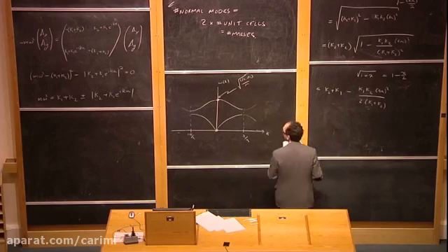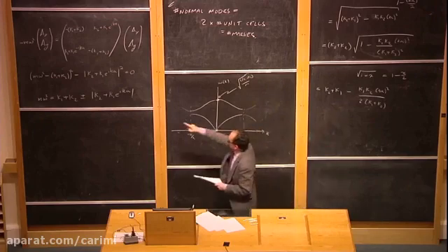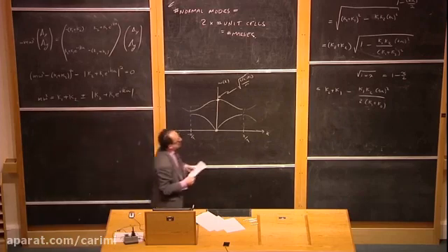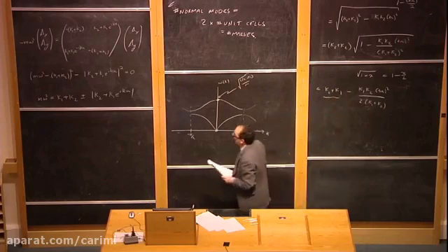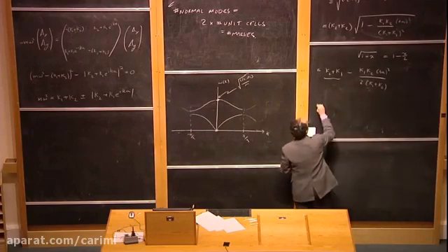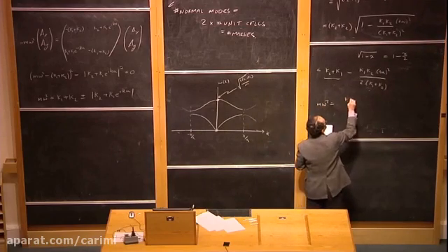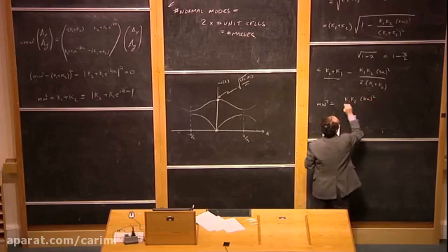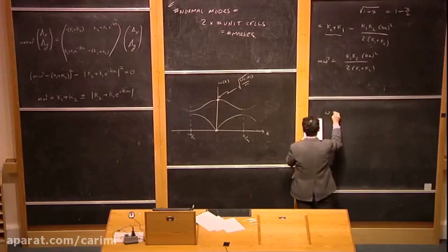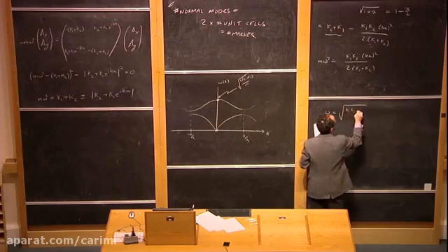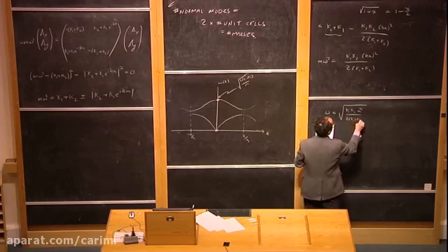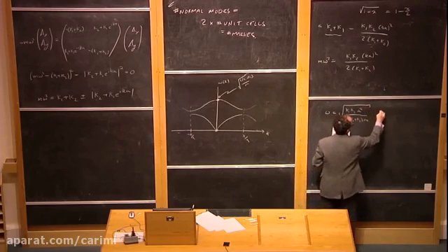So, all right, if I plug that into here, we see that the kappa 1 plus kappa 2 with the minus solution cancels this, kappa 1 plus kappa 2 also will cancel this, and we'll end up just getting m omega squared equals kappa 1 kappa 2 k a squared over 2 kappa 1 plus kappa 2, or equivalently, omega is the square root of kappa 1 kappa 2 a squared over 2 m kappa 1 plus kappa 2, times absolute k.